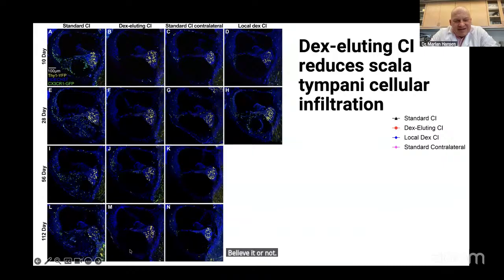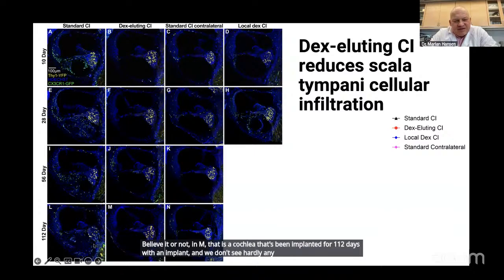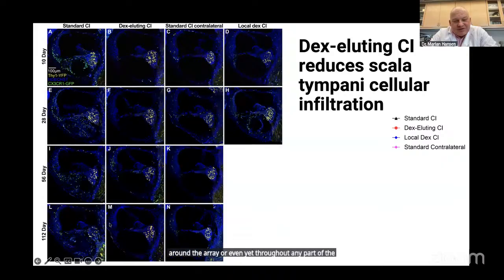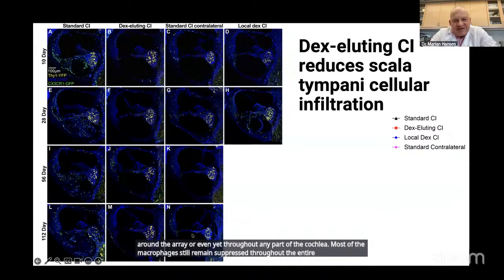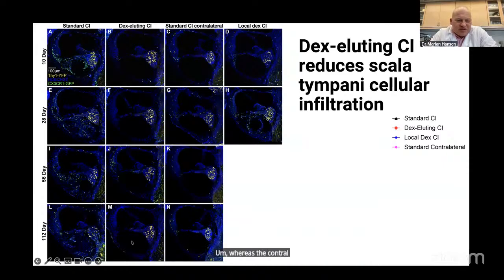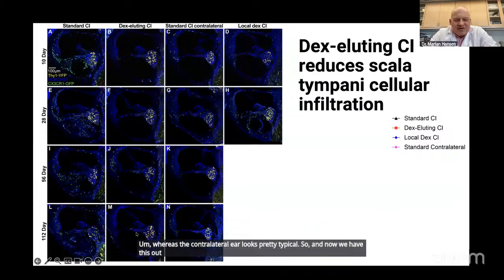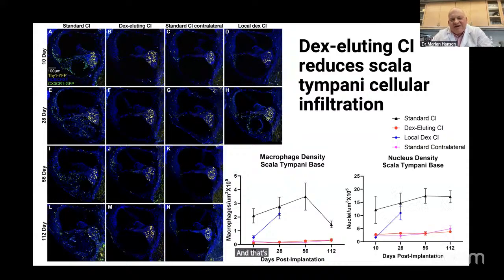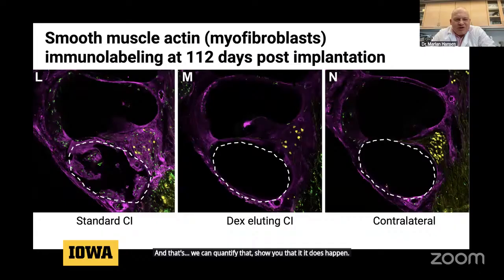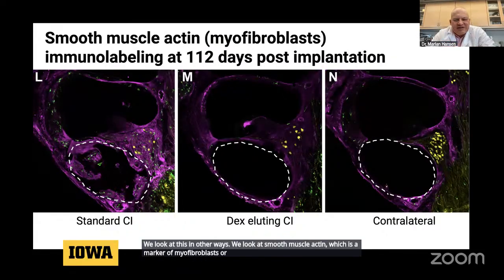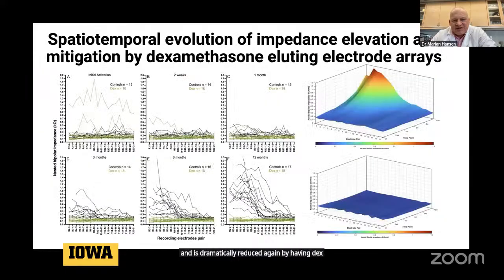Believe it or not, in M, that is a cochlea that's been implanted for 112 days with an implant, and we don't see hardly any immune response around the array or even throughout any part of the cochlea. Most of the macrophages still remain suppressed throughout the entire cochlea, whereas the contralateral ear looks pretty typical. Now we have this out to a year, where the dexamethasone elution is suppressing this pretty vigorous immune response to the electrode array. We can quantify that. We also look at smooth muscle actin, which is a marker of myofibroblasts or fibrosis, and that sits on the edges of this immune response and is dramatically reduced again by having dexamethasone-eluting electrode arrays.